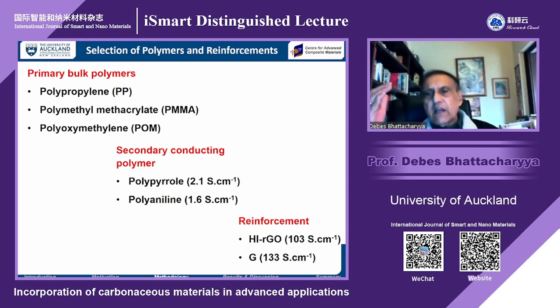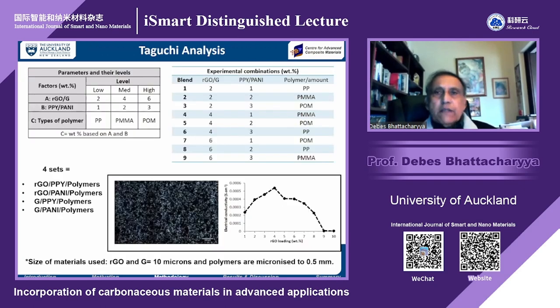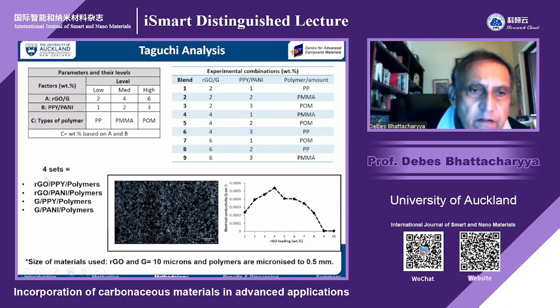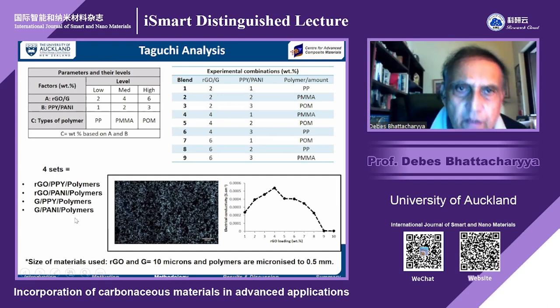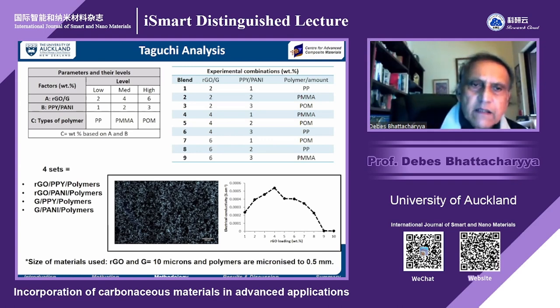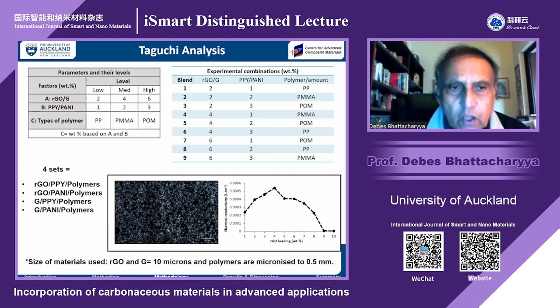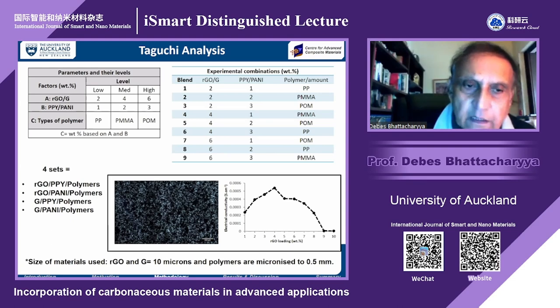RGO we manufactured ourselves. We could get up to 103, 105 siemens per centimeter. And the graphene that we purchased from two sources, one from China, one from Spain, both gave around the same, 130, 135 siemens per centimeter. So we tried some kind of experimental analysis, or Taguchi analysis. We combined four sets: reduced graphene oxide, polypyrrole and polymer; reduced graphene oxide, polyaniline and polymer; graphene, polypyrrole and polymer; graphene, polyaniline and polymer. We varied the combinations, and I am not going into those details. As long as you get a snapshot of the type of results we are trying to get. So RGO and G both were used, both polypyrrole and polyaniline were used, and then some kind of polymer.